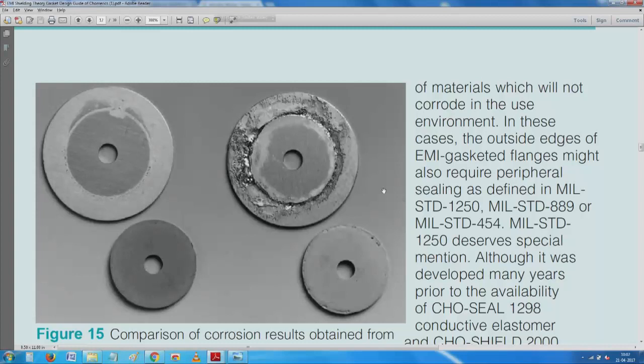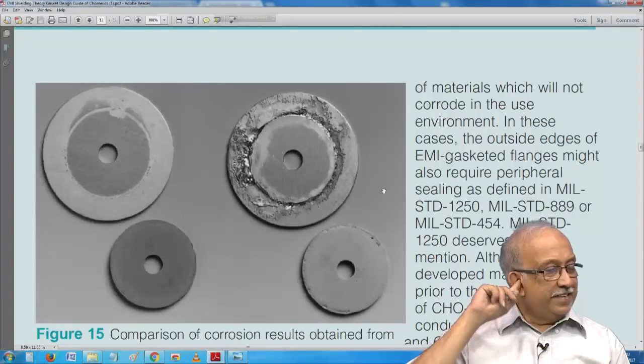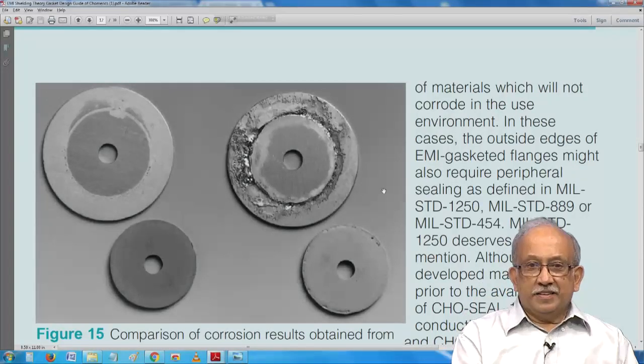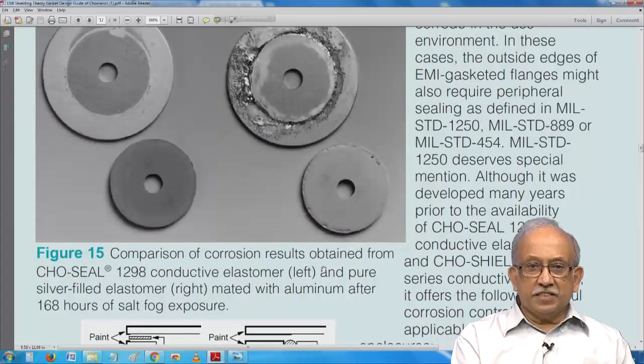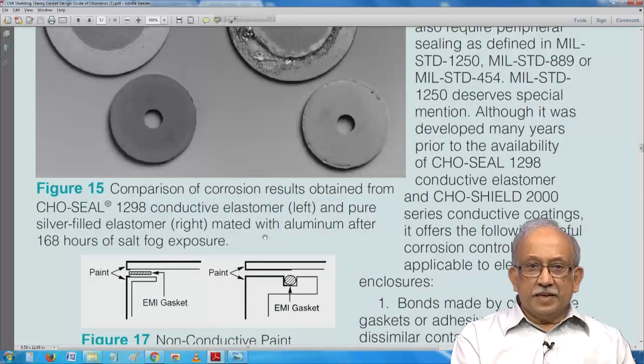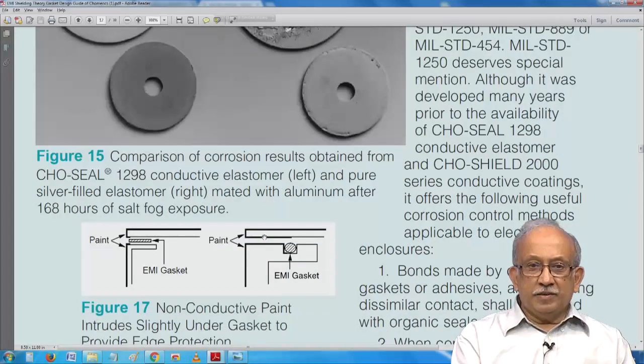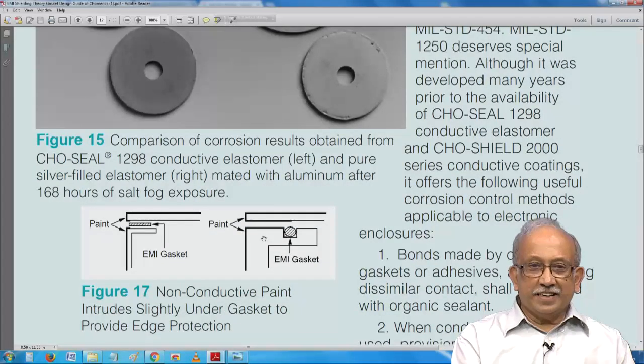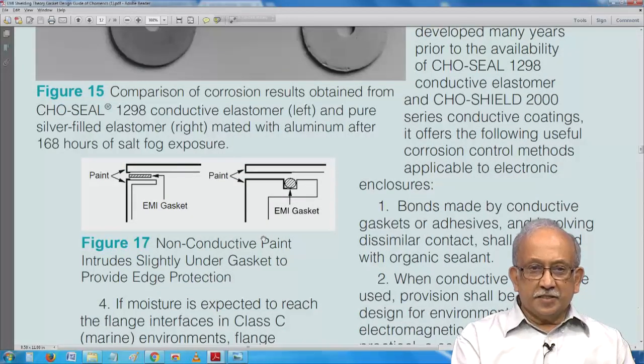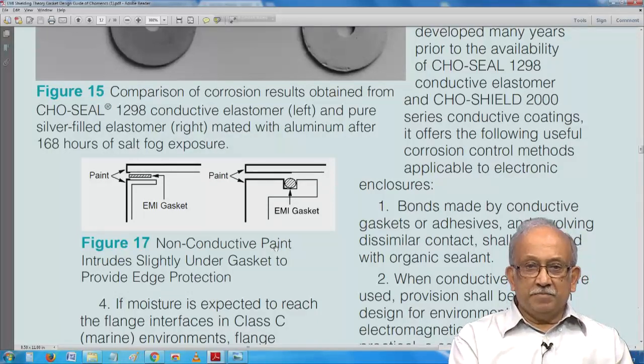You see around the edge where it is exposed to the atmosphere and can get all the necessary moisture, it has corroded all around the edge. The center does not seem to be so bad. Comparison of corrosion from CHO-SEAL and pure silver filled elastomer with aluminum. This I will not say is not real, it is individual case specific. Every time there are minor variations, including the clamping pressure and the ambient conditions.